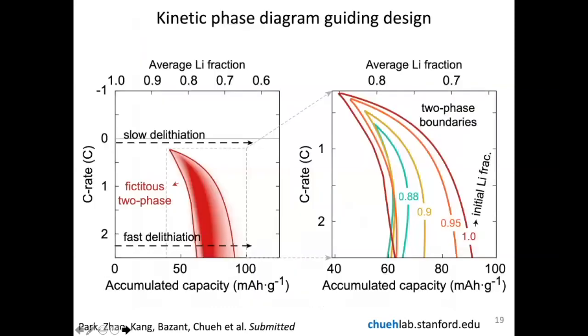So coming back to some of the design rules, now we know the importance of the reaction limitation, we can make a plot of the phase diagram under kinetic conditions. This is a phase diagram showing you the C rate on the y-axis and the amount of lithium extraction on the x-axis. So you can see that when you discharge, nothing happens. You're in a single-phase solid-solution uniform regime. But when you charge the material, when you remove lithium, you can run into what we call a fictitious two-phase coexistence between particles under an intermediate lithium regime. And this also depends very strongly on what lithium composition you access.